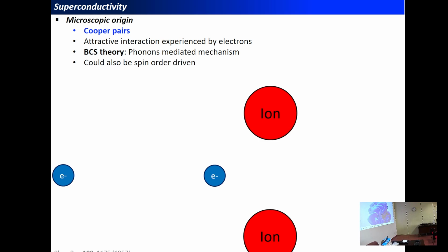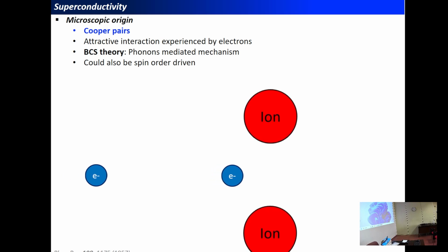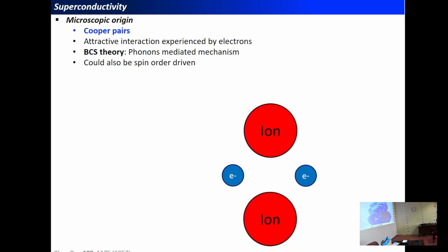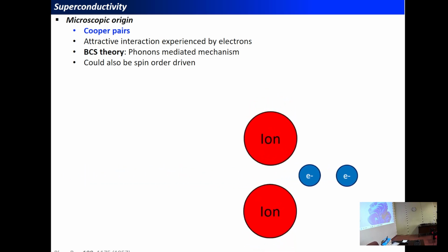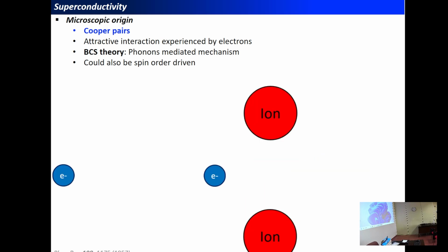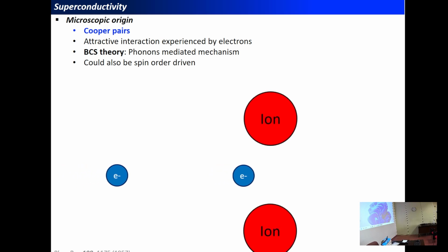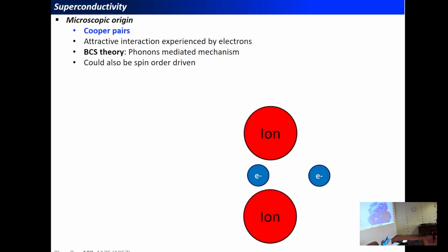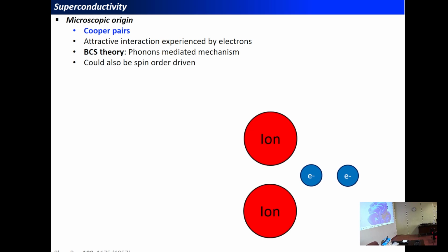When an electron is flowing through the material, it approaches the lattice, and so it's exchanging momentum with the ions, and they react. This electron is losing momentum, and the other one is attracted by the two ions, and so is gaining momentum, and so the two electrons can be close together and form a Cooper pair. That's the main mechanism, which is phonon-mediated, but in some other systems, such as the cuprates, it can also be spin order driven, but this is still under debate.